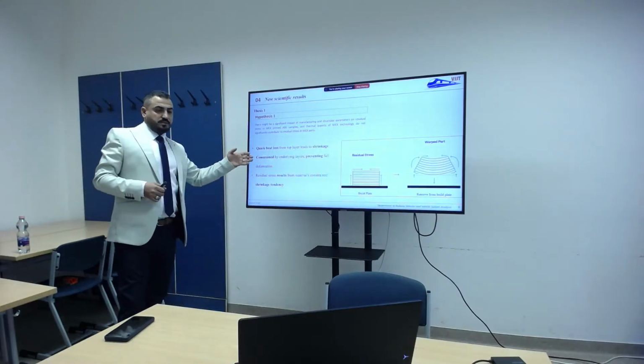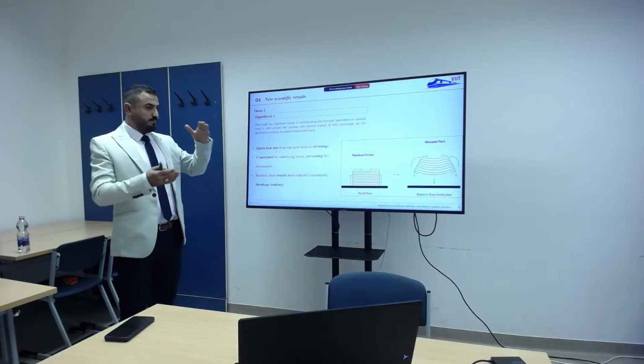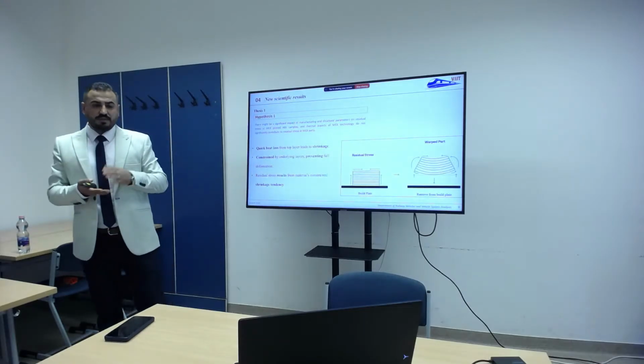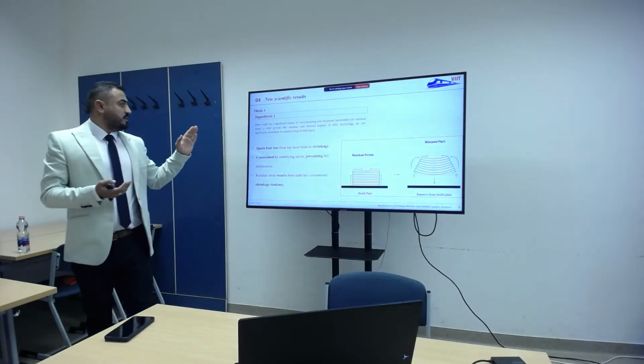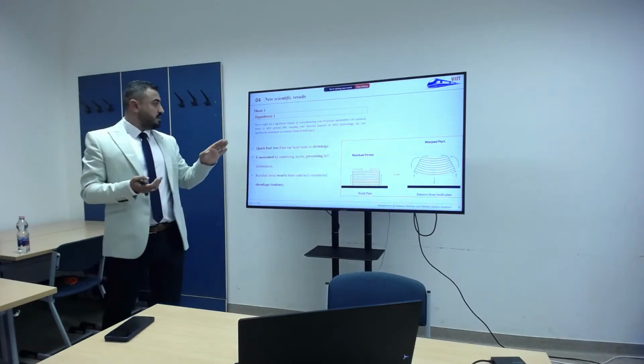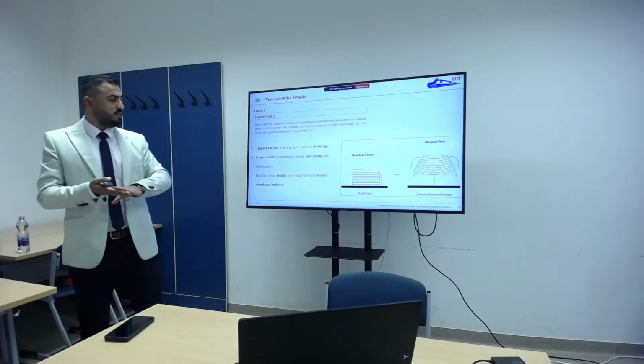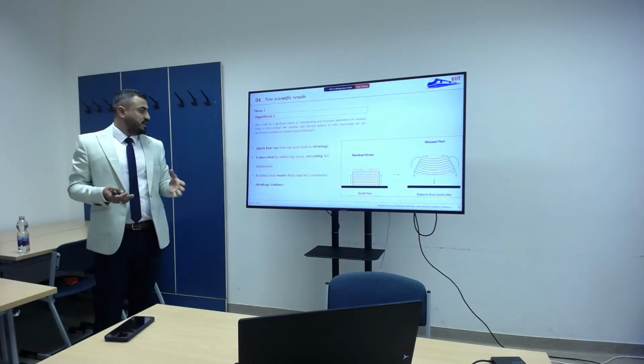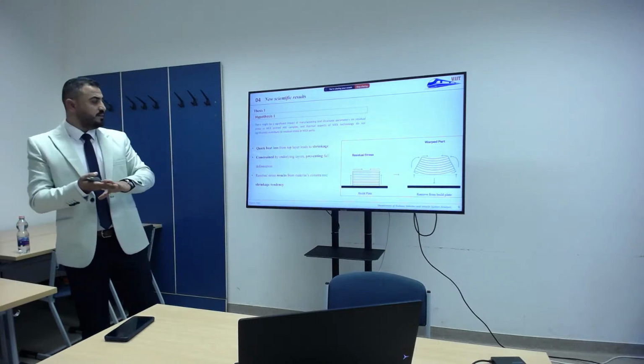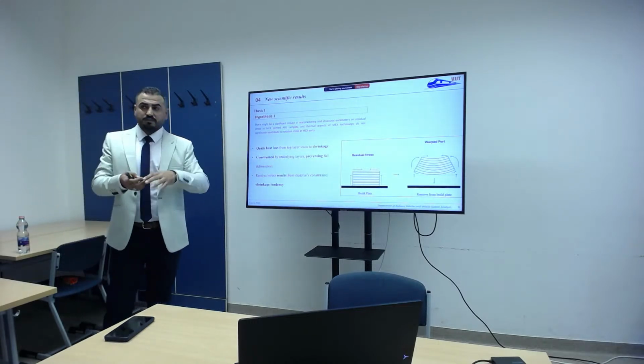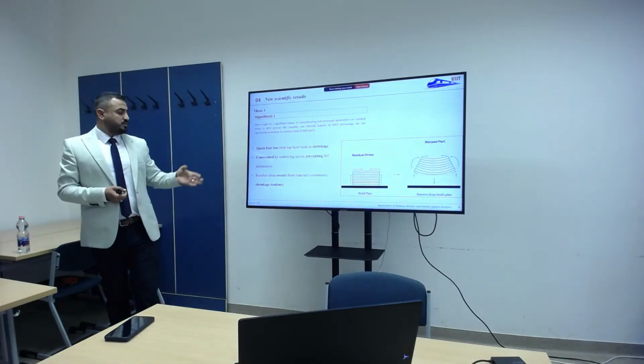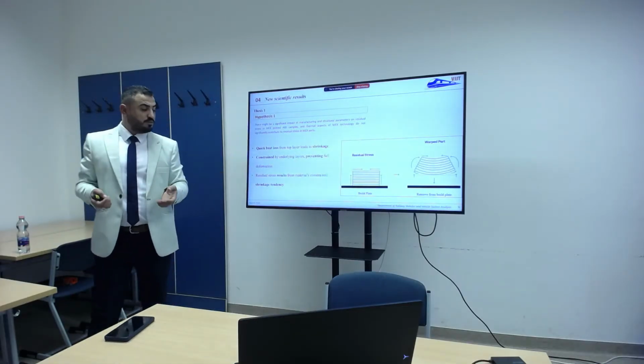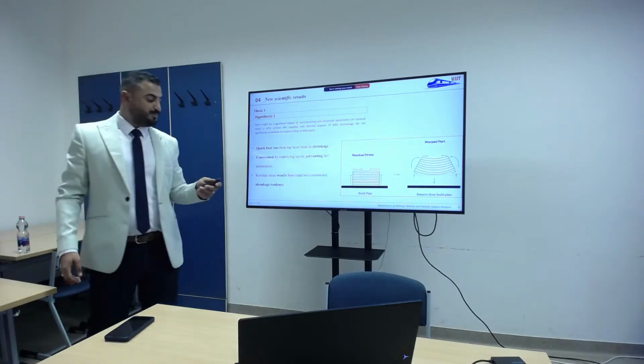In the beginning, let's talk about residual stress. Because of the process of 3D printing, there's quick heat loss from the top layers because it's deposited, and this leads to shrinkage. These constraints by the underlayer prevent the full deformation of the new layer. So the residual stress results from this material constraint on the shrinkage tendency.